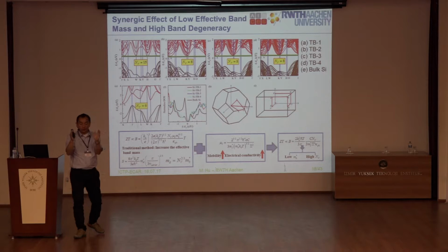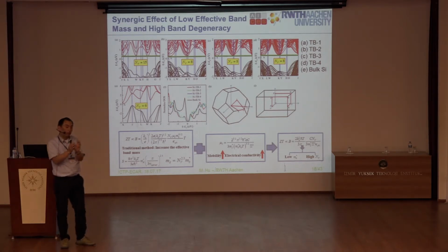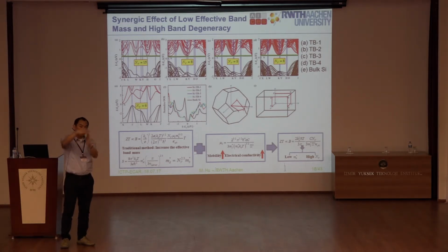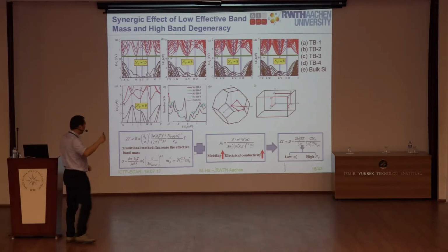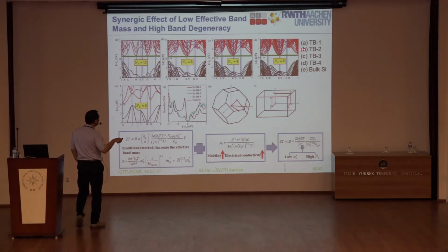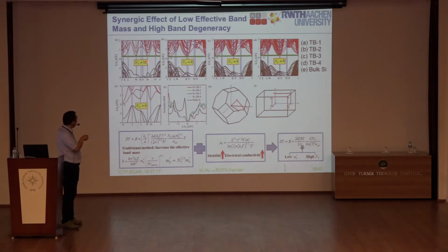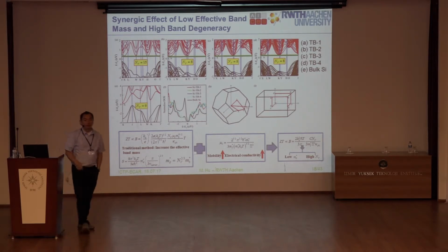Because you can also think of the nano-twin structure as some kind of special superlattice structure, right? You have this AB and BB periodicity, right? And then you can find that as the periodic length decreases, the band degeneracy increases, and then you have a very, very high value. So the mechanism is that although we have a relatively low effective mass, the band degeneracy is so high that eventually the Seebeck coefficient enhances. So that's the mechanism.